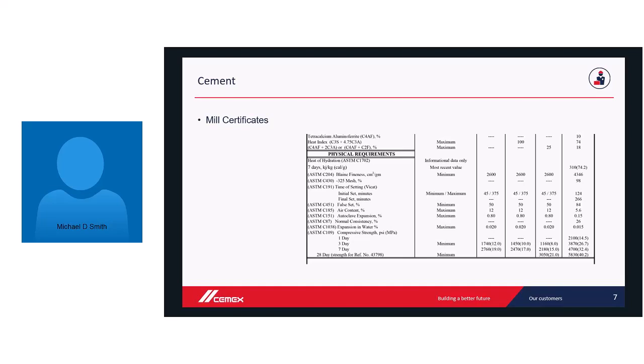And then probably your next most important would be your compressive strengths. Different markets for cements produce different compressive strengths. Some of them will focus on strengths achieving in 1 to 3 days. Some of them don't care about early strengths and focus more on later strengths of 28 days. Arizona market, for whatever reason, maybe because of the temperatures out there that they experience, that market tends to focus more on getting heavy strength early. So it tends to shift a lot of the strength gain in the 1 to 3 day range, whereas out here it's more of a 28-day focus in California.